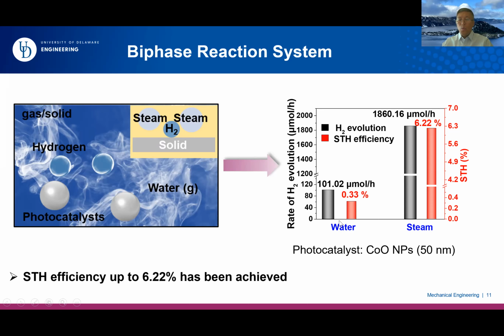So we simply compare liquid water and steam. You can see the solar-to-hydrogen efficiency goes from 0.3% in the triphase system to more than 6%, so more than 20 times higher. That of course is related to the hydrogen evolution process, which also increased by 18 times. So that just simply gives you an example to show this.